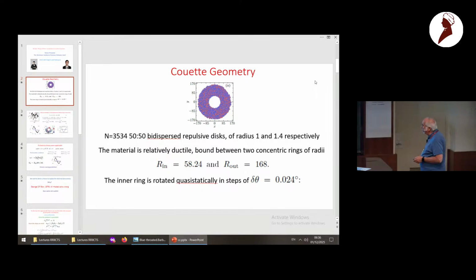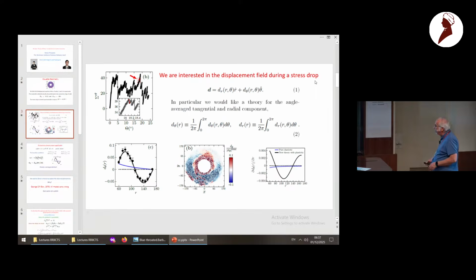And now the inner ring is rotated quasi-statically. What does it mean? For those who don't know, you rotate a little bit and then you energy minimize. You rotate a little bit and you energy minimize. So you do it quasi-statically, such that after every step, the system is brought back to mechanical equilibrium, and the changes in angle delta theta are very small, 0.024 degrees. Okay, so very small, very small, very small. Still, you accumulate stress.